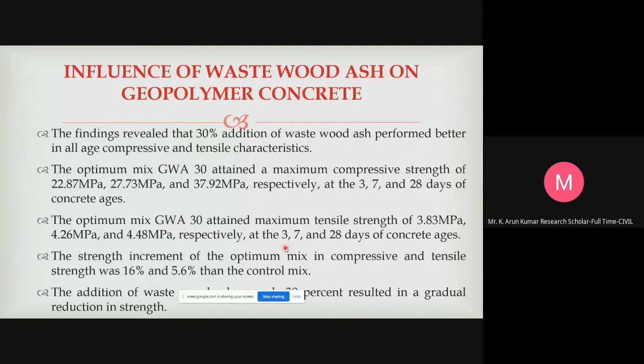And by the same method for tensile strength, we have obtained 3.83 MPa at 3 days, 4.26 MPa at 7 days, and 4.48 MPa at 28 days. The strength increments observed were 16% for compressive strength and 5.6% for tensile strength compared to the control mix, which is having 100% fly ash.